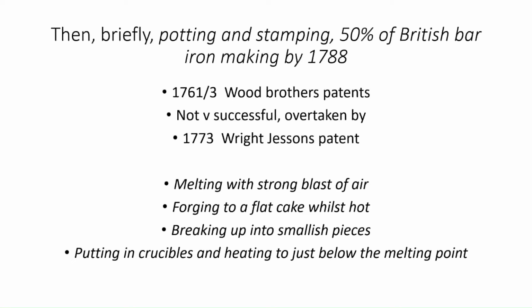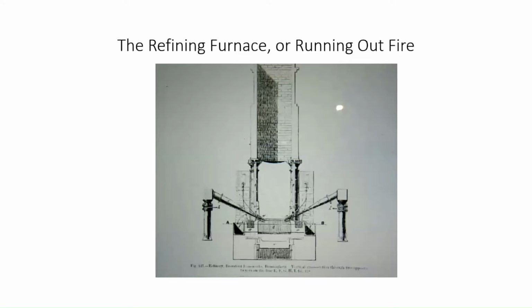Okay, yeah. So this is the question then. Up until 1760, 1770, I had to use charcoal to make the transition, but they developed a method first of all, in the 1760s, the Wood brothers developed a process which was known as potting and stamping, but that wasn't very successful, and it was rapidly overtaken in the 1770s by the Wright-Jessons process. And what they did here was get rid of the silicon first by putting it in what was known as a refining furnace or a running out fire. And this was basically a pile of coke on which they put the pig iron, blasted it with air, and heated up to a point where it melted and ran out, as it were.